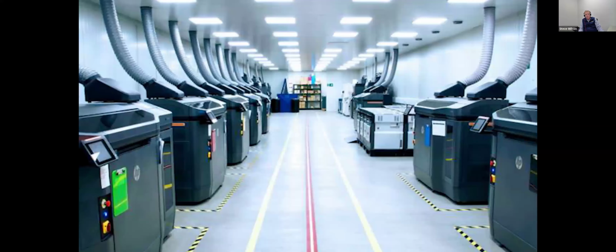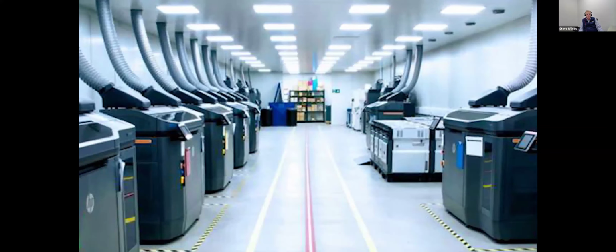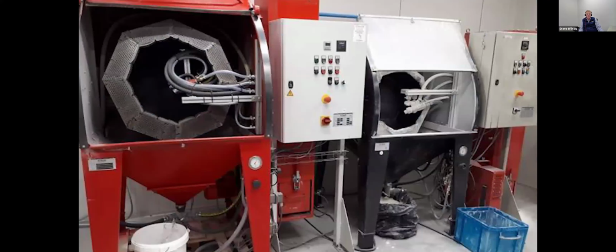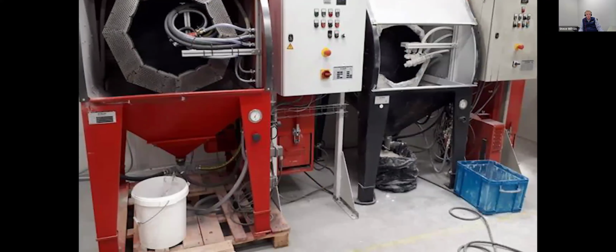If you're into additive manufacturing, 3D printing, we do a lot of post-processing. Generally, it's powder removal or support structure removal. In this case, on an HP printed part, it's powder removal. It's gentle enough to remove the powders without damaging the printed part.